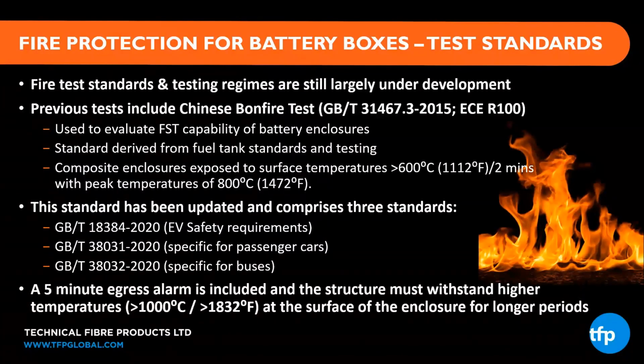Previously, the key standard was the GBT 31467, also known as the Chinese bonfire test, which was originally derived from a fuel tank standard and was a really stringent standard to pass, with temperatures of 600 degrees centigrade for up to 2 minutes and a peak of 800 degrees C. This has now been updated to a suite of 3 standards, with GBT 38031 really being the lead standard for passenger cars. And this standard is even more stringent, with a 5-minute egress alarm and higher test temperatures of up to 1,000 degrees centigrade.